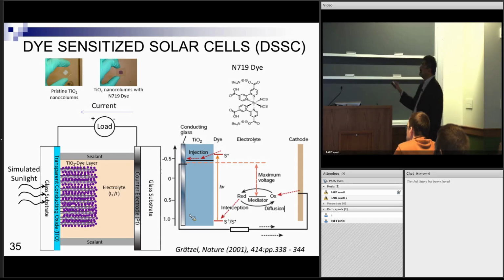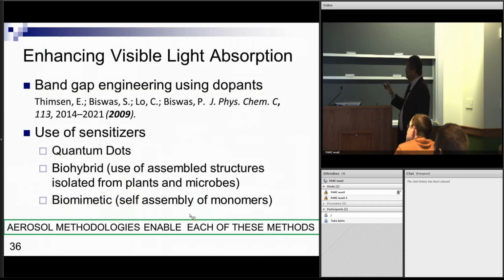So sensitizers are very effective. You can absorb more sunlight in the visible spectrum, and here are our columnar structures just seen by the eye, and then when you coat it with the dye, and you can see the dye molecules are well distributed. So even for a conventional dye system, this is quite nice in terms of the morphology, and people are preferring one-dimensional type structures. You can engineer the band gap.